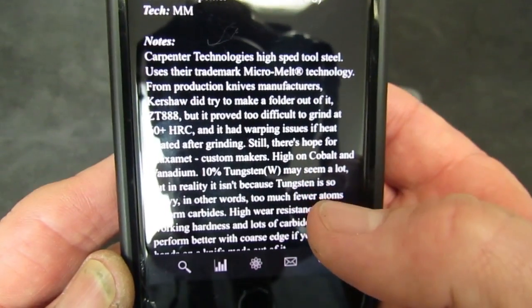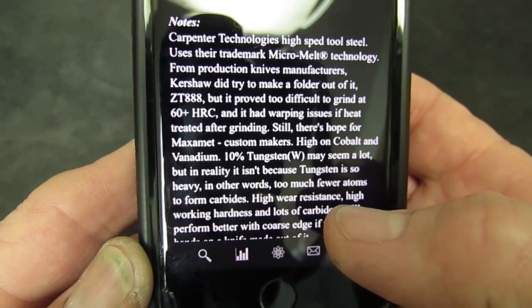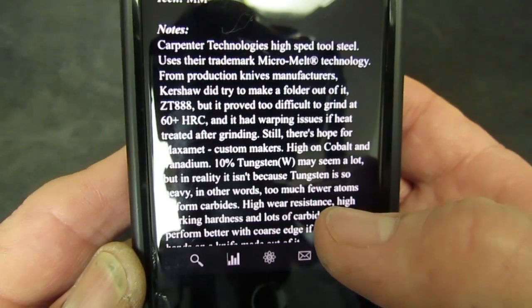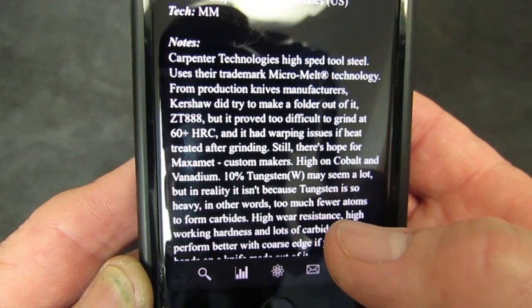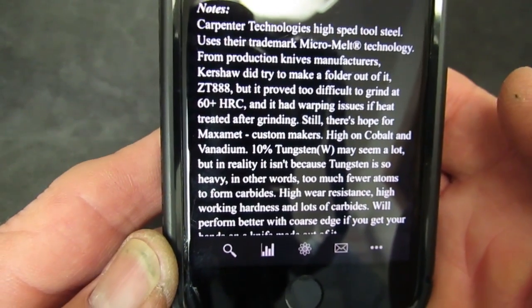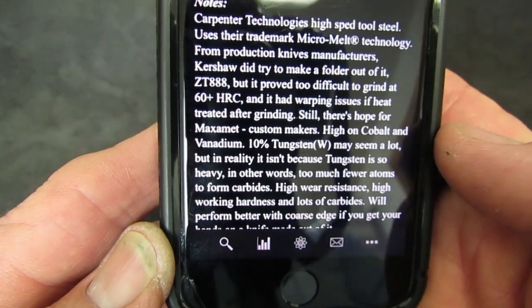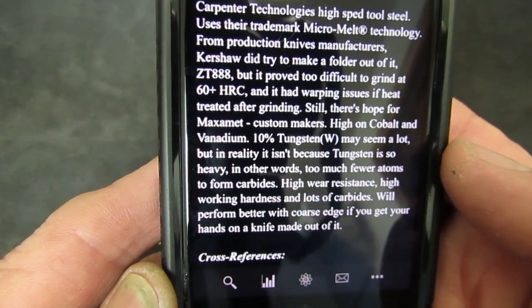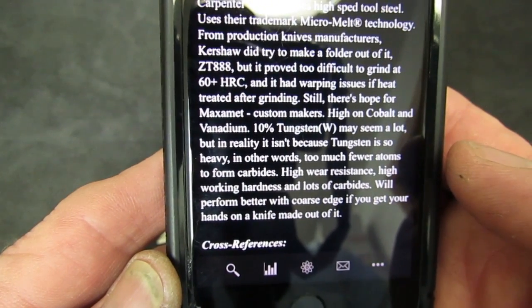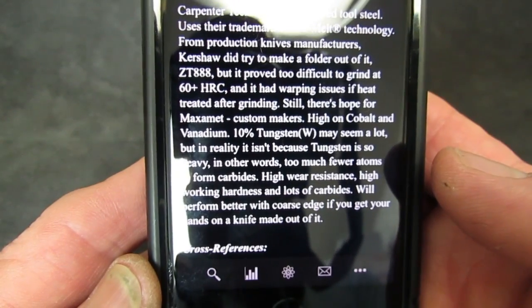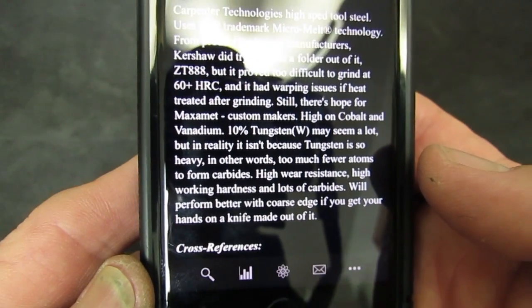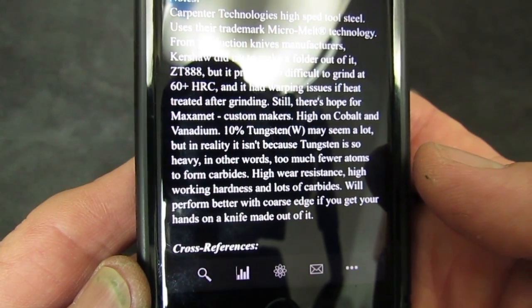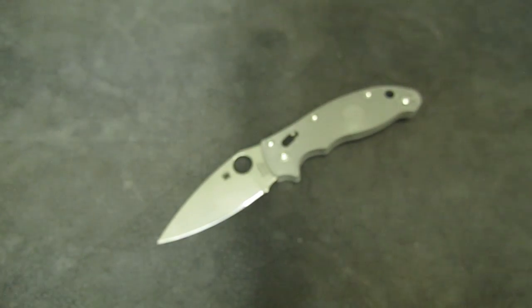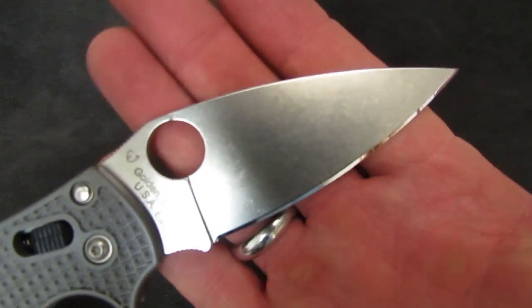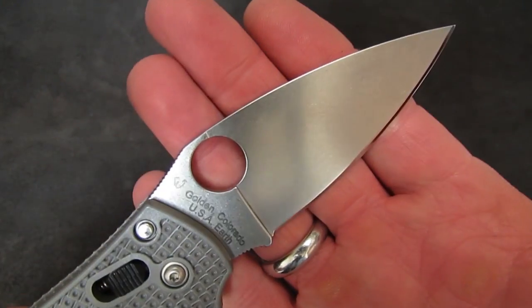Still, there's hope for Maxamet custom makers. High on cobalt and vanadium, tungsten. 10% may seem like a lot, but in reality it isn't, because tungsten is so heavy. Meaning a lot of tungsten in weight, which is how the percentages are measured, doesn't mean a lot of tungsten in the structure. Okay. So it has high wear resistance, high working hardness, and tons of carbides. Lots of carbides. Will perform better with coarse edge if you get your hands on a knife made out of it. What this text doesn't say is that Maxamet is of extremely low toughness,